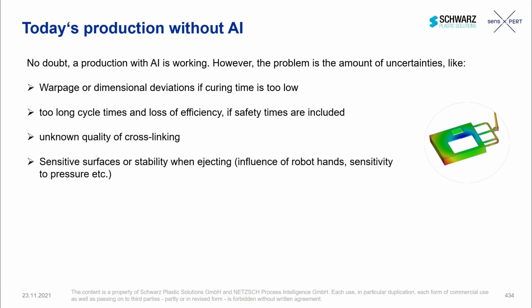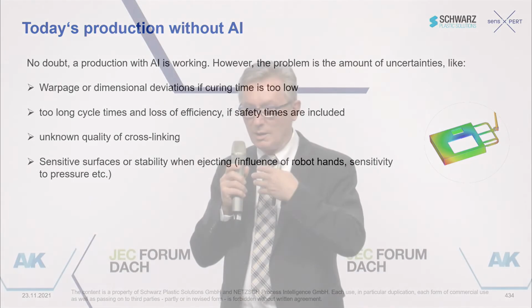we will check, and you see the product here on the side, let's say a case or a box, whatever you want to call it, with different wall thicknesses and different gate positions, because all of the 4 gates can be either opened or closed. So we can really do a lot of different process variations with, in that case, one complex mold. And therefore, we can find out what happens in real life when cycle times are too short, when injection speed is too high. That means too much shear and therefore too much heat comes into the reaction process, and you get a sudden cross-linking, which you would usually like to avoid.